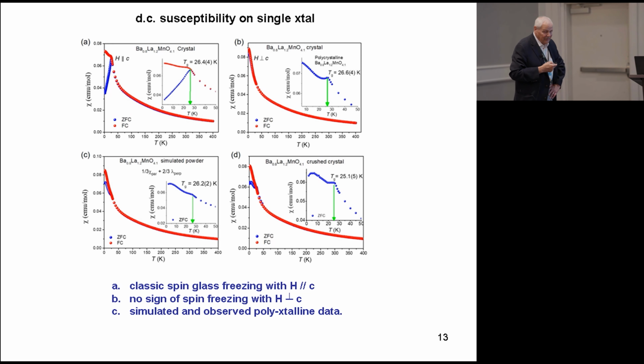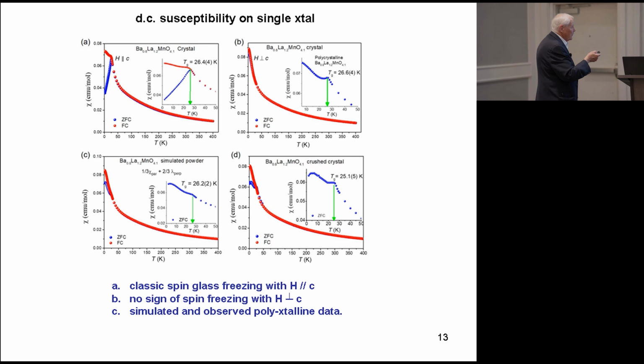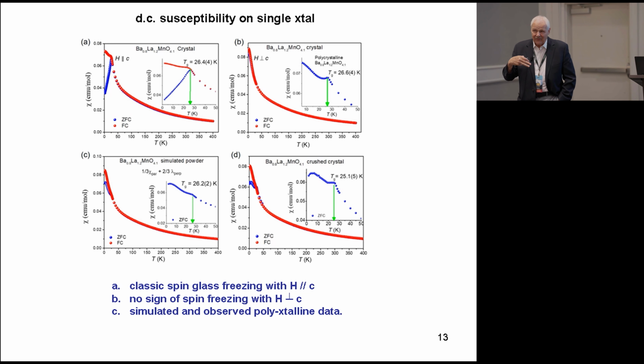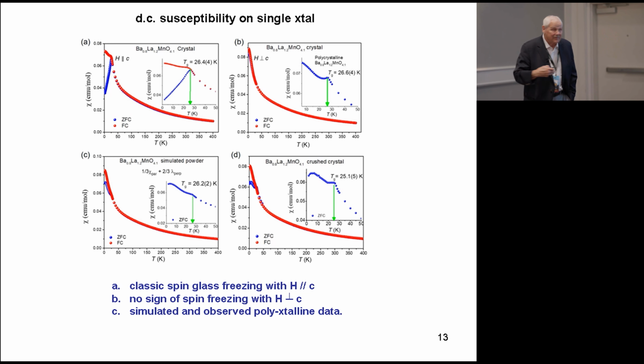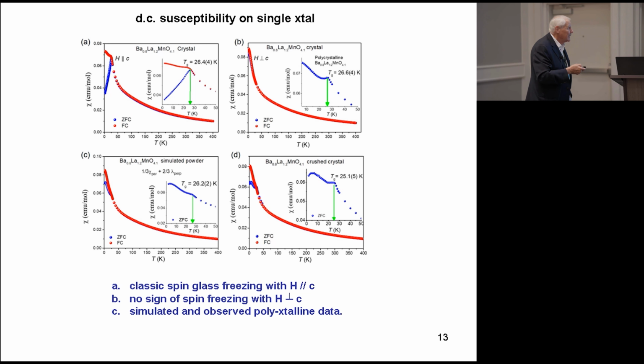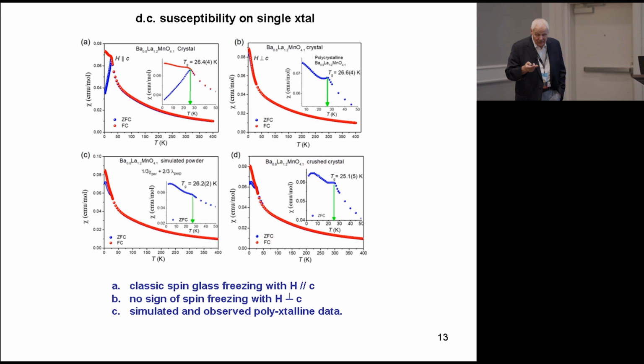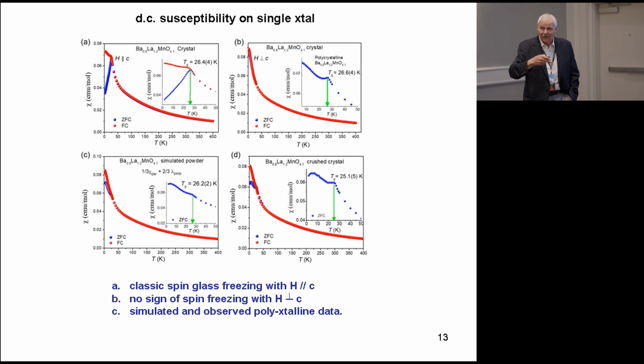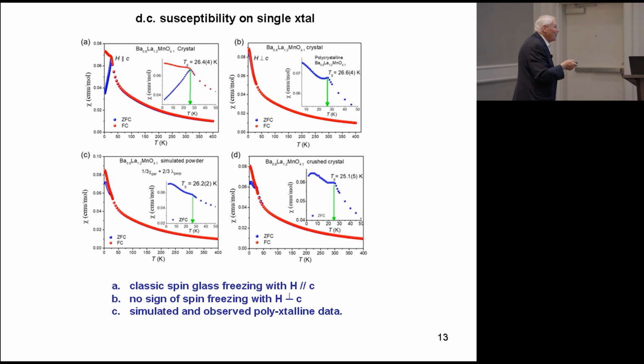If we measure its susceptibility with the field applied along the z-axis, we get what is basically classic spin glass behavior. I'll show you some other evidence for that. So this is perfect spin glass behavior. When we apply the field normal to the z-axis, we get no spin freezing whatever, down to a base temperature of 2 Kelvin. The other two slides are just efforts to show what we should see in a polycrystalline sample, because we're clearly not going to grow crystals of all the compositions. We tried once and it didn't work out that well.